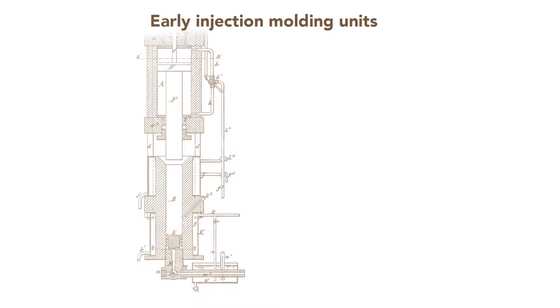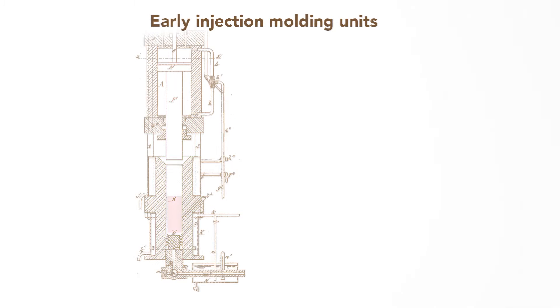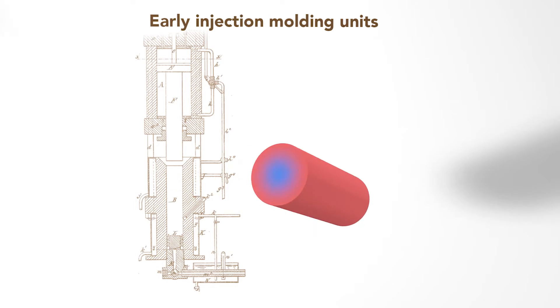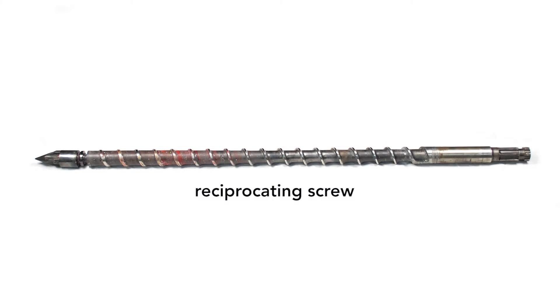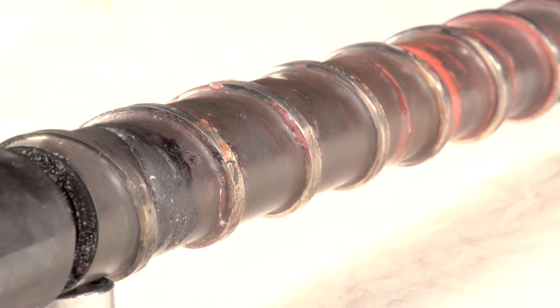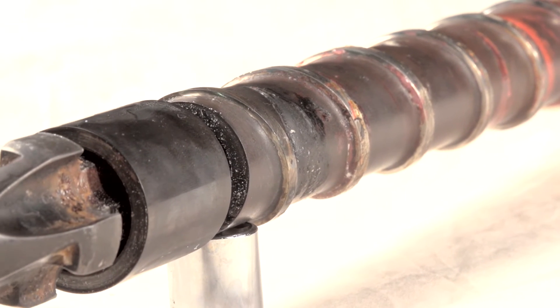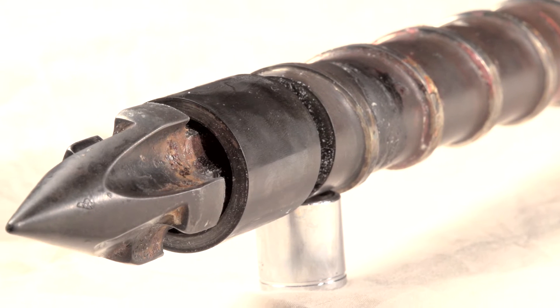Before the mid-20th century, injection molding machines used only external heating of the barrel to melt the plastic before a plunger injected the molten material. But because plastic conducts heat poorly, the temperature was uneven in the barrel — either the middle was too cool and not fully melted, or the outer regions were too hot and degraded the plastic. The solution was the reciprocating screw, often regarded as the most important contribution that revolutionized the plastics industry in the 20th century. In the earlier plunger-style machines, plastic filled completely the cylindrical barrel, but the plastic was not at a uniform temperature.